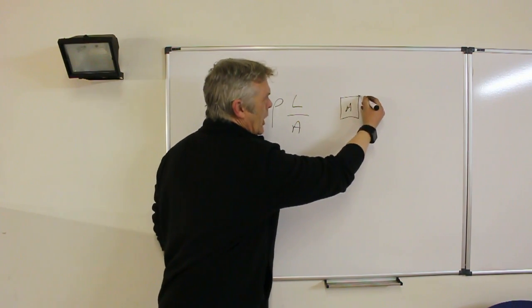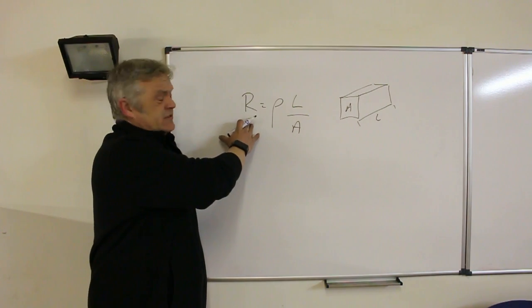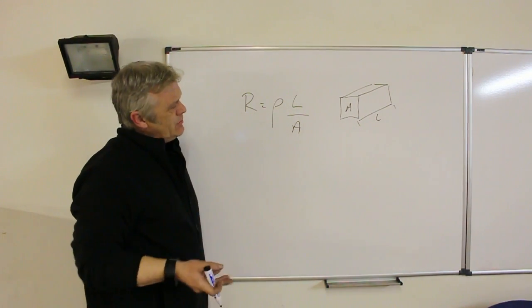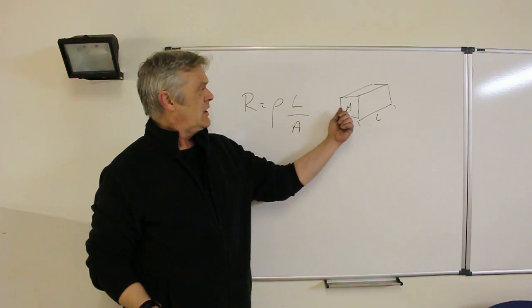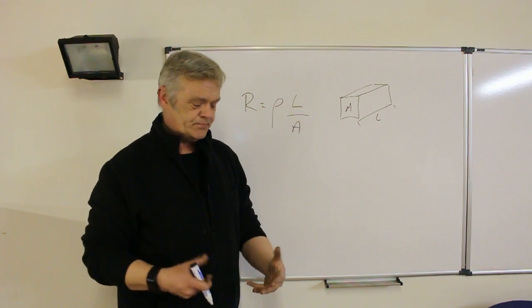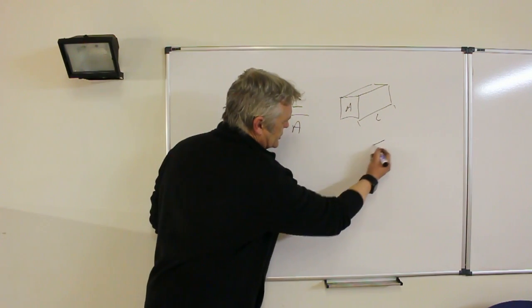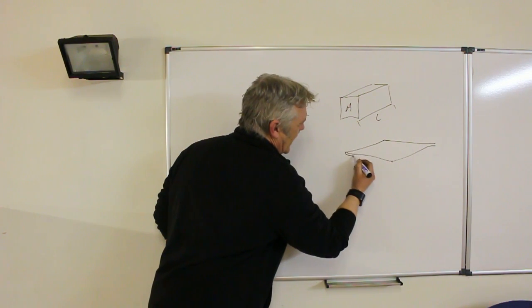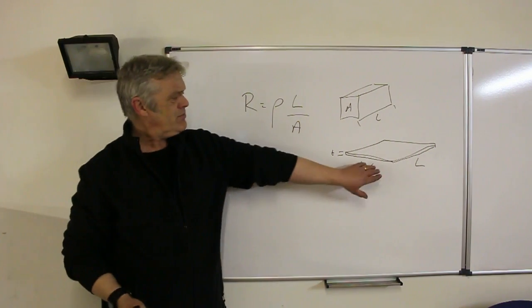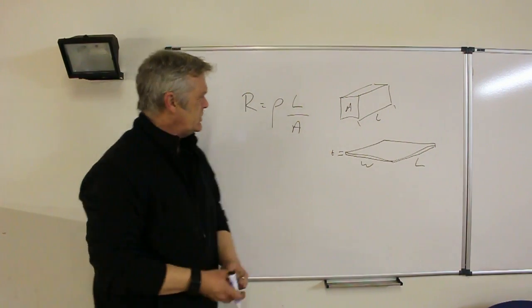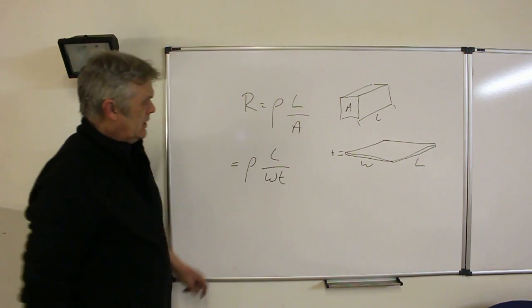A block of material has an area, a length, and those geometrical factors affect the resistance of the overall block. When measuring resistance of a bulk material, you take a one centimeter by one centimeter by one centimeter block, attach a couple of copper plates, and take the resistance across them. Now this doesn't quite apply when looking at sheets. Sheets are of uniform thickness — a large plane with some length, some width, and a thickness T. So resistance becomes rho times length over width times T.